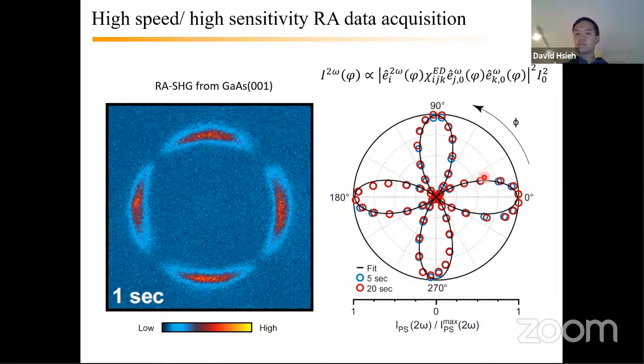And just like one perhaps would do in diffraction studies, you can reduce your chi tensor under various point group symmetries and go ahead and fit your data. So we take a bunch of these types of data under different polarization geometries, for example, and we do a universal fit to chi, and the best fits are how we determine the appropriate point group symmetry of the material, okay?